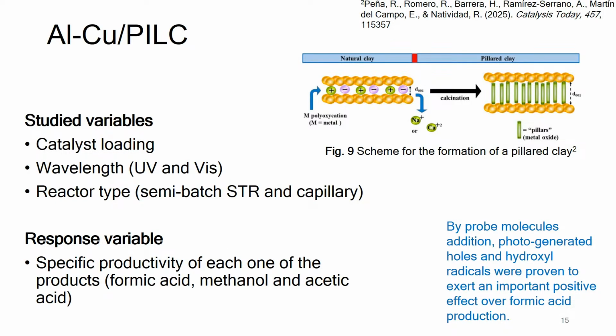The other catalyst that I'm going to present in results is the aluminum copper pillared clay. In this case, these were the studied variables. And here I'm showing you how the aluminum silicate layers are formed. And here in the interlaminar spaces, we conduct an ionic exchange. There is sodium or calcium, and then we input metal cations like copper or iron. And the result is this. And again, we focus on the production of formic acid, although we also obtain methanol and acetic acid.